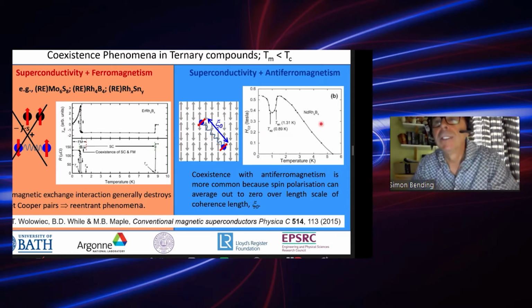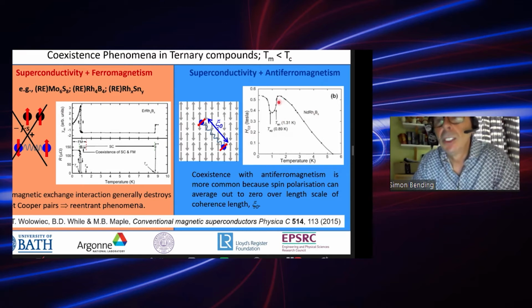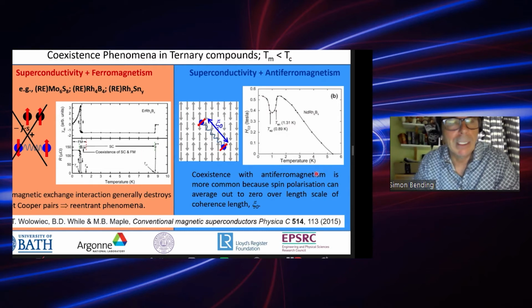And here I show an example taken from the neodymium rhodium boride system, which actually shows two antiferromagnetic transitions. Here I'm plotting the upper critical field as a function of temperature, and you can see quite a strong suppression of HC2 as the antiferromagnetism turns on, but it nevertheless survives very easily. And these examples were taken from this very nice recent review paper from Wolowicz et al.